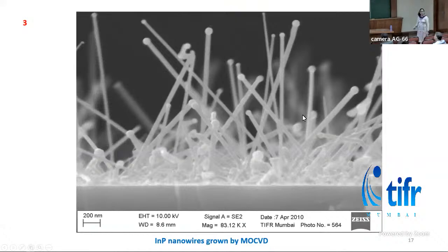Here is an example of indium phosphide nanowires grown using MOCVD. So here also we check for the length and diameter of the wire. We check the wire orientation with respect to the substrate, and also the composition of the wires and the catalyst tip.